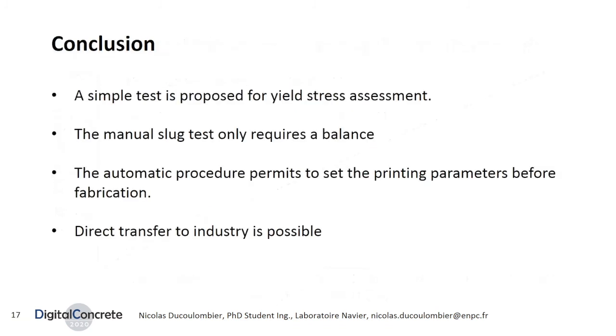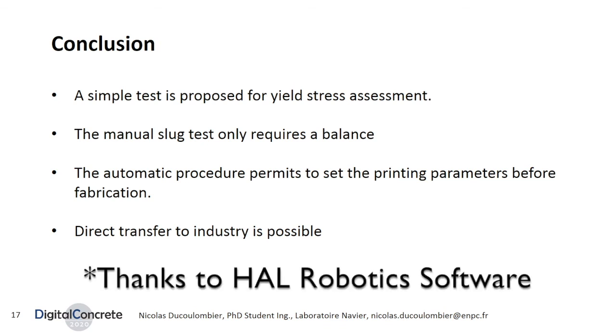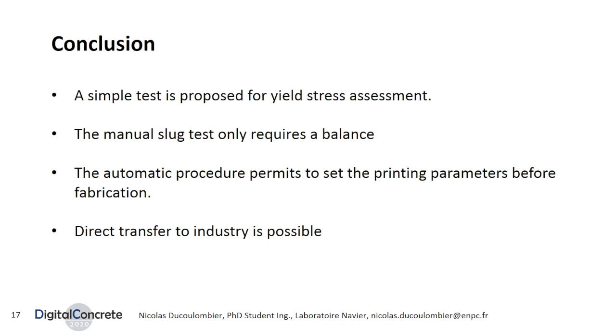To conclude, we introduce a simple test for direct inline assessment of yield stress at the nozzle level for extrusion-based additive manufacturing. Two different protocols are proposed. The first one is manual and only requires a container and a balance. The second one is an automatic procedure permitting to automatically estimate the yield stress and the confidence interval. The automatic slug test is currently performed just before each fabrication in building facilities to adjust the printing parameters with the actual yield stress and flow rate measurements. Finally, a direct transfer to industry is possible. In fact, a similar system is currently being installed in XtreeE facilities.